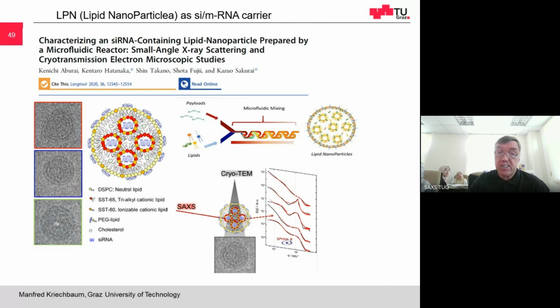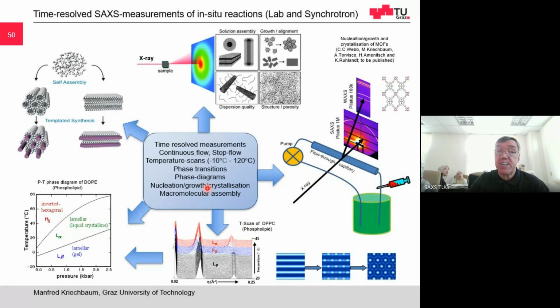I think I'm coming closely to an end. Here's just summarizing what you can do by time resolved SAXS measurements. You can do reactions in situ. So you can make a batch reaction and pump your solution continuously through your X-ray beam, and then you can measure nucleation and growth. You can use heating stages to map out phase diagrams, and you can also monitor self-assembly by time resolved X-ray diffraction or small angle X-ray scattering. So there are many possibilities: static and time resolved, static and dynamic.